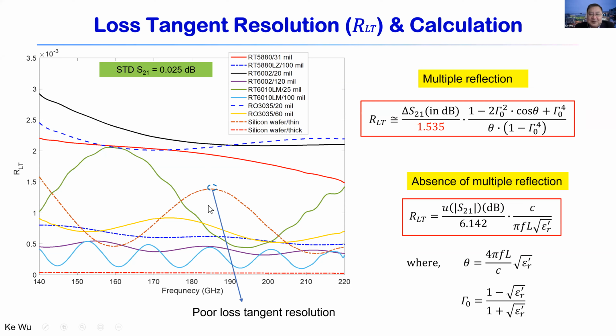And this is particularly important, for example, for these multi-reflection models, which are usually very good for thin substrate or thin layer structures, for the thin substrate material test. But for a thicker substrate, for a thicker wafer, for example, we don't need to use the multi-reflection models, because there's no need for that. So in this case, we can simplify the analysis.